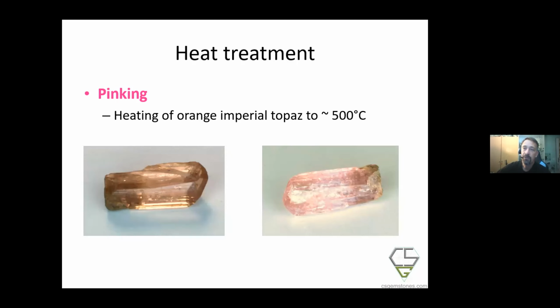And now we have to understand a little bit of physics and chemistry, because we know that an element like chromium doesn't change by heating. It might change its oxidation state, but in case of chromium, it doesn't. It stays the trivalent chromium. However, the yellow color centers, which are distortions in the crystal lattice, can be erased by heating the topaz to higher temperatures. The lattice starts to vibrate at higher temperatures, and a lot of the defects dissolve into nowhere. Let's put it this way: you can erase the history of the treatment. So the yellow goes away and you're left with the pink. And therefore this process is also called pinking.